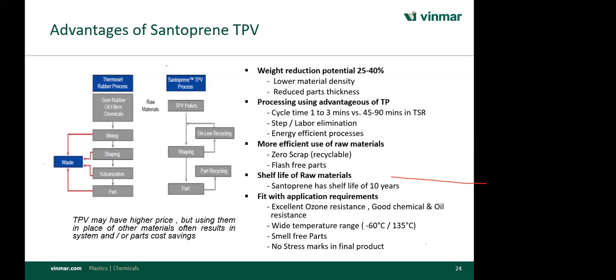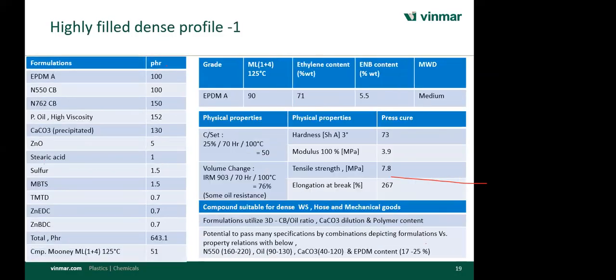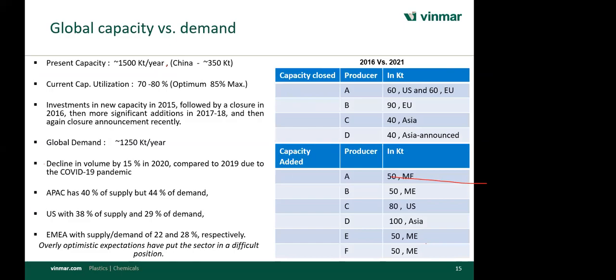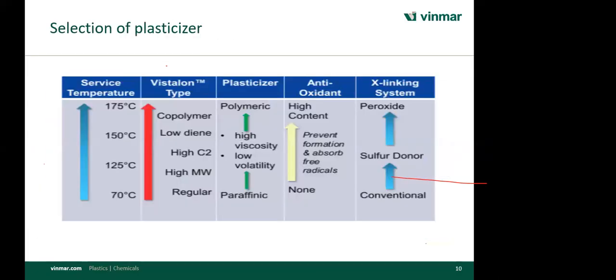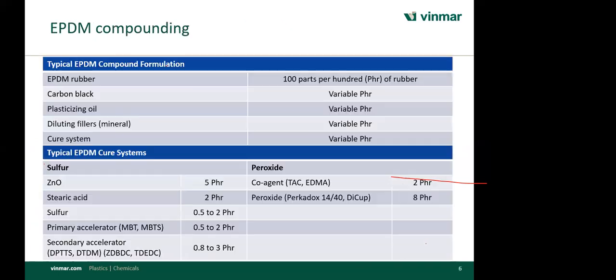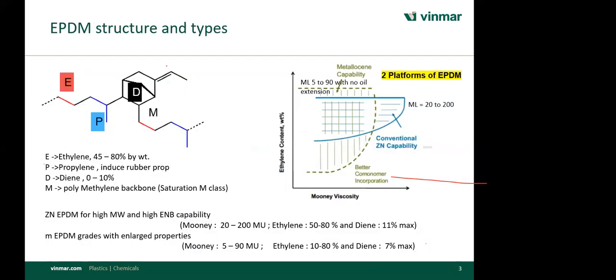So the next question is, how to increase the tear strength of EPDM compound? For tear strength, you have to reduce your mineral fillers. Still, if you are not getting a satisfactory result, then go for high molecular weight EPDM. High molecular weight means, again I'm going back to my first slide probably. So this is the high molecular weight. If you switch over to the Ziegler-Natta system of EPDM, like oil extended EPDM, you will get excellent tear. If your molecule is high, then you cannot break it down.